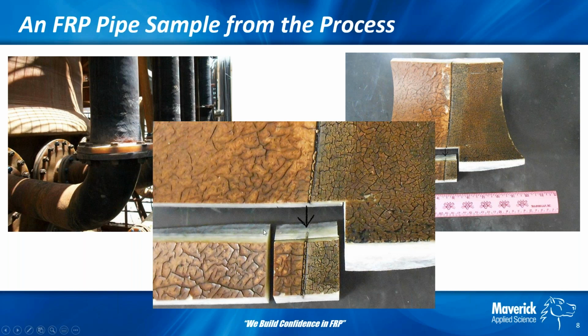One interesting point is you'll see the joint line here where this is the elbow and the straight pipe meet, and you'll see that ruffled line in between there. We found, or at least believe, this to be basically the resin coating on the end of the pipe. So it gives you an idea of what that looks like after almost 20 years. It actually nearly separated, at least for the depth of the corrosion barrier, but is still remnant in the joint space.